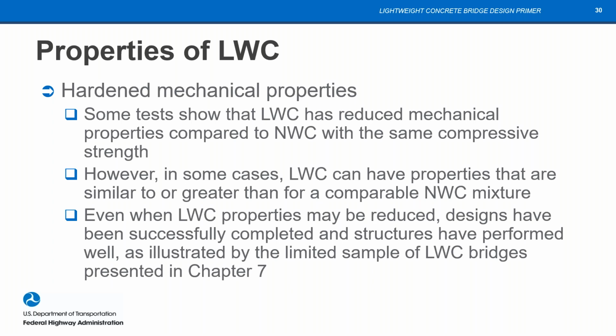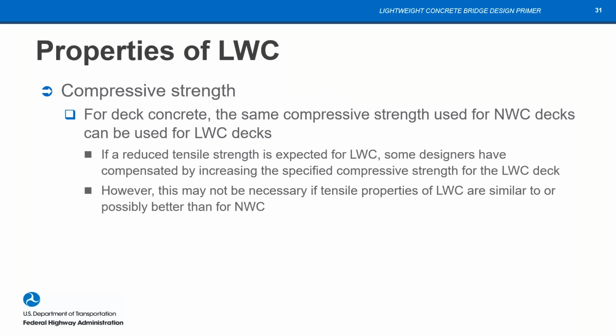Well, in production, out in the real world, you would just bump up the cement content a little bit for the lightweight, and you'd end up with the same compressive strength. So that's just something to bear in mind. Looking at lightweight concrete decks, we can typically use the same compressive strength that we use for normal weight decks. That's easy, no problem to achieve for a lightweight deck. In a few cases, people have increased the lightweight concrete strength because they think that we have a reduced tensile strength for lightweight. That's a possibility, but we'll see some data that refutes that later on.